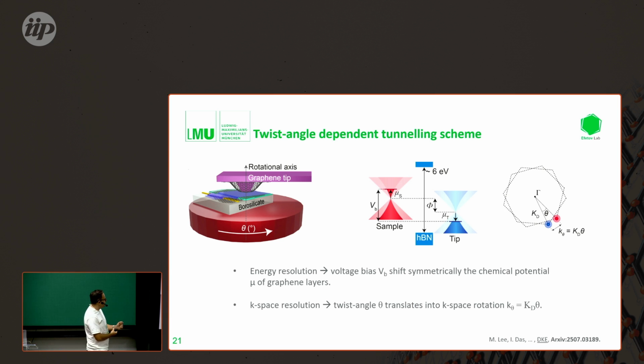And the tunneling configuration you can just see here. We're applying a bias between sample and tip. If you do an electrostatic simulation, this bias goes almost in equal parts into the doping of the sample area and the doping of the tip area, and then there's also some electrostatic drop across the hBN substrate here.